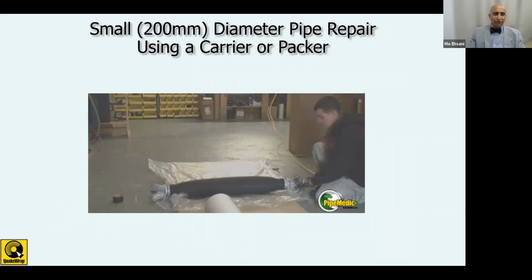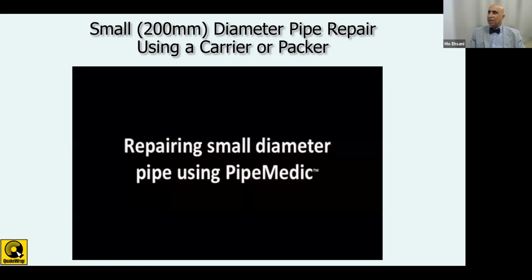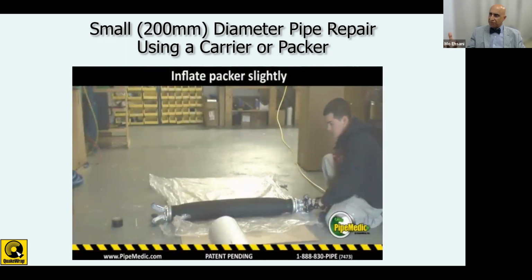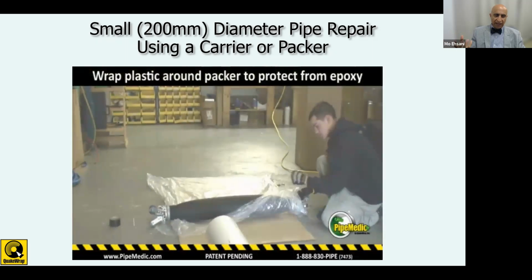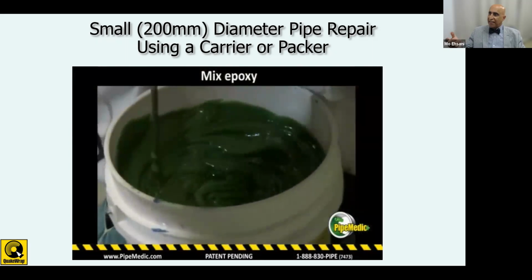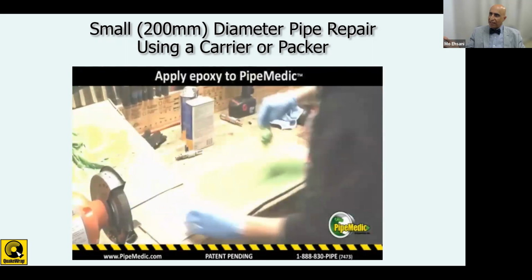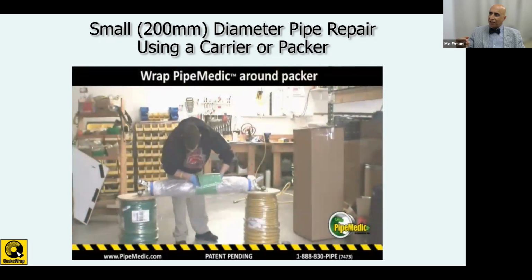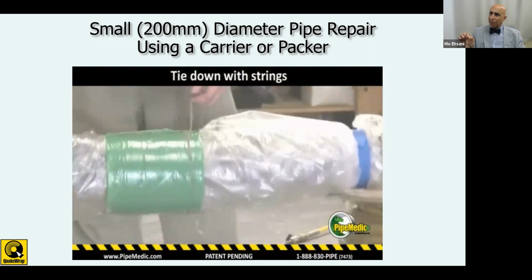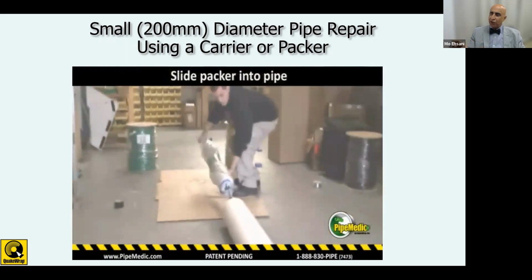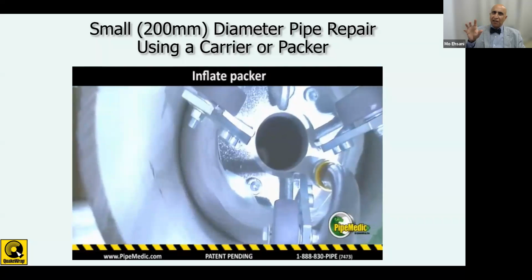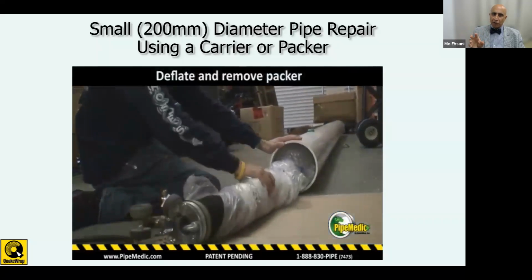So one type of application of these is for internal repair of pipes. As you see here, when the pipe is small and doesn't allow man entry, in this case, we can take a laminate. We use these packers, which are these balloons that you see here being inflated. We inflate the balloon and take a laminate and put this epoxy on the back of that laminate, and then wrap that laminate around the packer, hold it together with a couple of strings, and then the assembly is sent into the pipe. And we usually, like with a closed circuit TV, monitor the location.